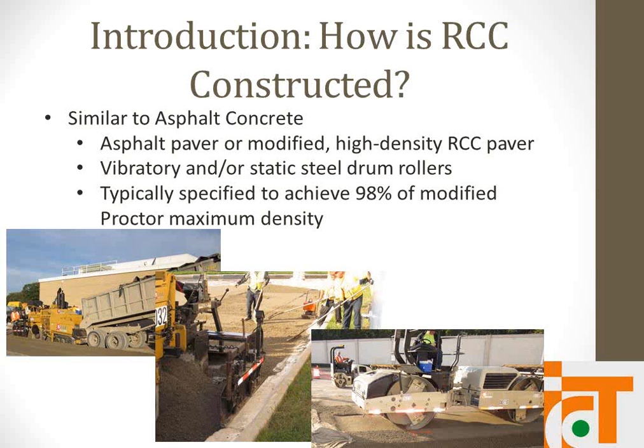And then afterwards, it's compacted with rollers. Typically, a vibratory roller goes over it first. That's seen in the bottom right. And then a finish roller, just a smooth static steel roller, will come behind it just to give the surface a nice finish. And density is the controlling factor. It's typically 98% of the modified proctor as measured by like a nuke density gauge.